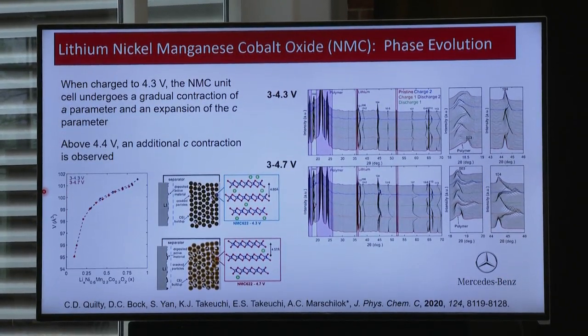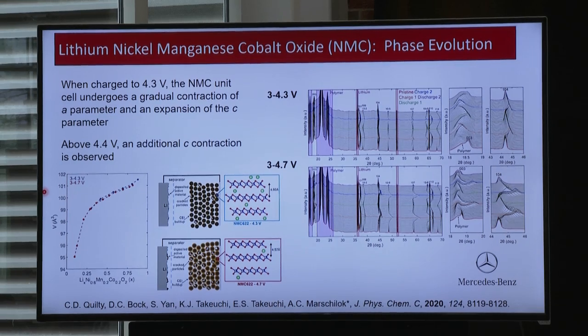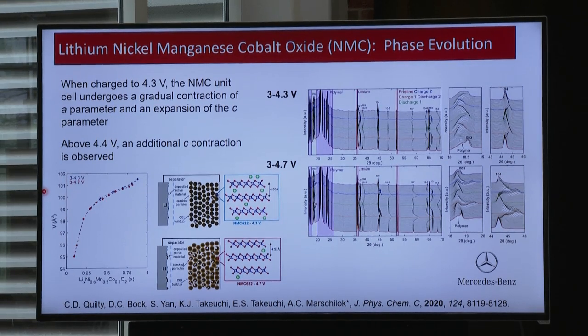We did a detailed X-ray diffraction study. In this case, we're using what's called operando X-ray diffraction. Operando means we have a working battery, and we're measuring it while it's working. So we're getting real-time data, and we looked at charge to 4.3 and charge to 4.7. What we found is that there's much more expansion of the unit cell, so the change in volume is significantly exaggerated when you go to 4.7.